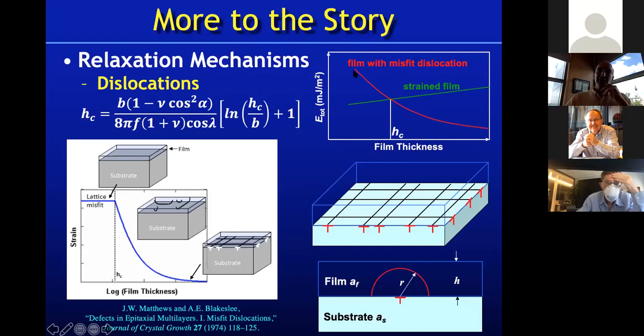So that's the red line here, how much it costs to introduce dislocations, and I look at this as a function of thickness. I have this one over thickness energy falloff of what I get from putting dislocations in the film. And you can see that energetically there's a stable point, where the material would go from a lowest energy state of being strained to a lowest energy state of being dislocated. And that calculation was done almost 50 years ago by John Matthews and Blakeslee in this classic publication. For those of you that are students, you probably have never heard of John Matthews, but maybe you've heard of his son, Dave Matthews, from the Dave Matthews Band. It is indeed the same Matthews. And what he calculated was the equilibrium critical thickness at which energetically the system would have a lower energy by being in this dislocated state rather than the strained state.